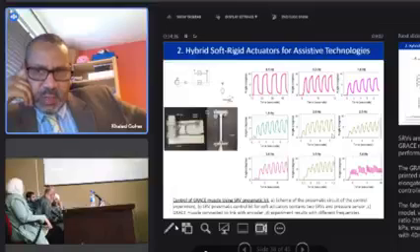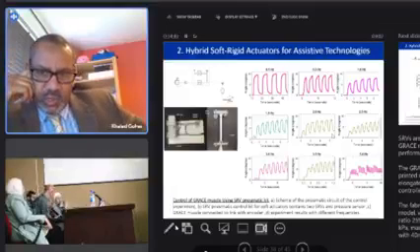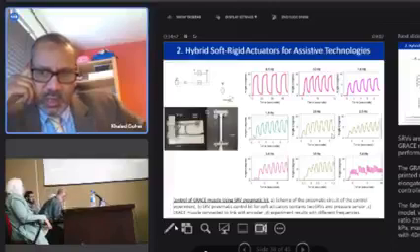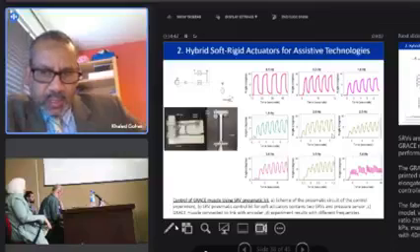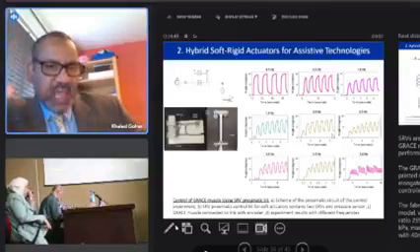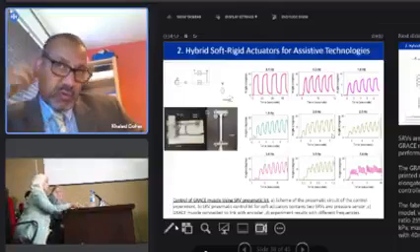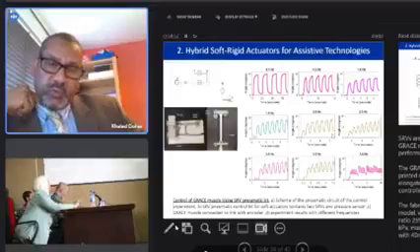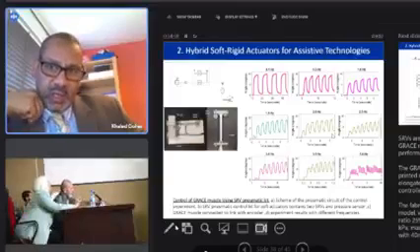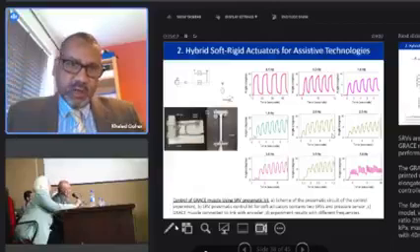A fabricated muscle is a contraction model, which can reach a contraction ratio around 25% when it is pressurized by around 26 kilopascal. It is made of a flexible resin. We used it for stereolithography. So this has mainly been produced by SLA 3D printing using flexible material with 40 millimeter height.